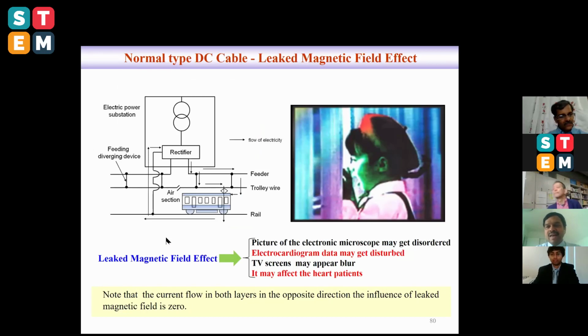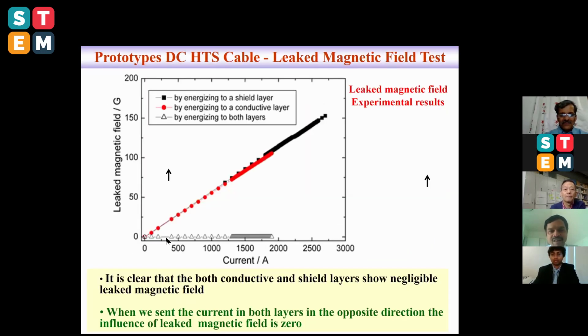But one more thing, from an application point of view, it is important to test the effect of the leakage magnetic field during the current flow, especially in Japan, since railway tracks are very close to residential areas. If the magnetic field is very close, almost all TVs cannot be clear, and also in hospitals, electrocardiograms will be damaged. Then we tried to see the leakage magnetic field: for both the conductor layer and the shielding layer, a negligible magnetic field was found. When we set the current in opposite directions, the leakage magnetic field is almost 0. Then we said, oh, it is very clear, it is perfect.